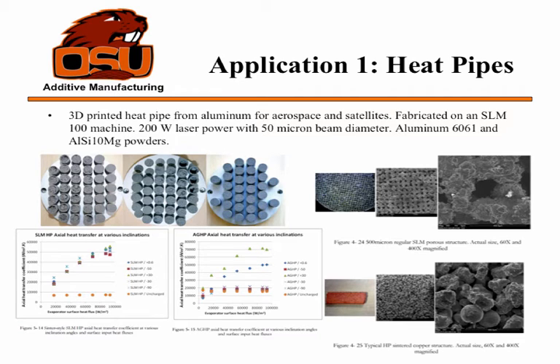And then as you get towards the right, you can actually see an entire build plate where they pretty much made successful porous wick structures and figured out those build parameters with laser power, exposure, beam diameter, etc. On the bottom left over here, you see the heat transfer. So the selective laser melted heat pipes with axial grooves.